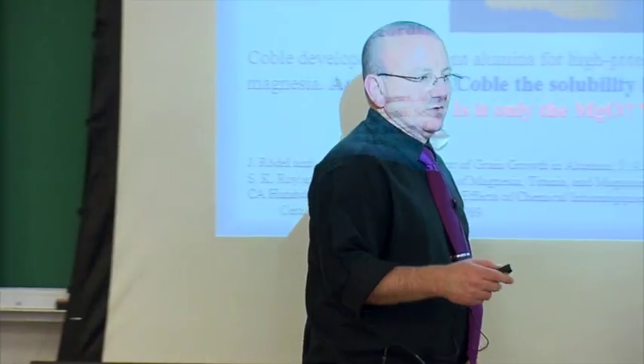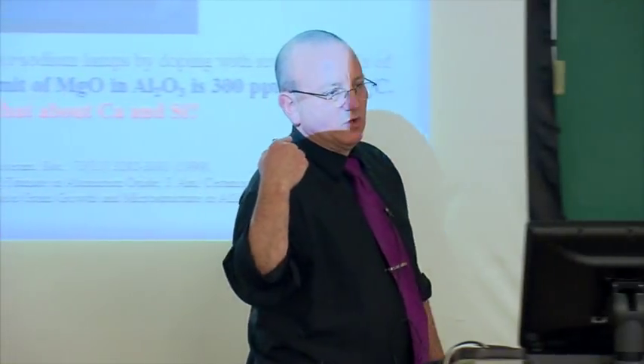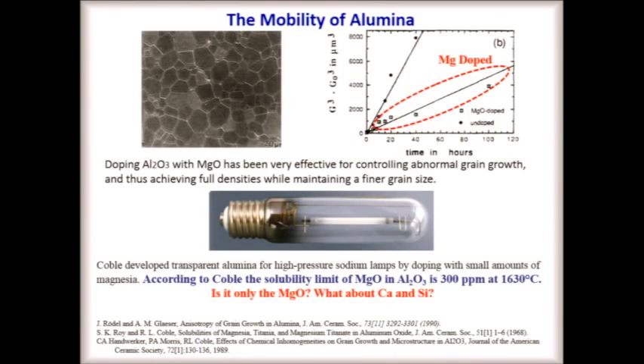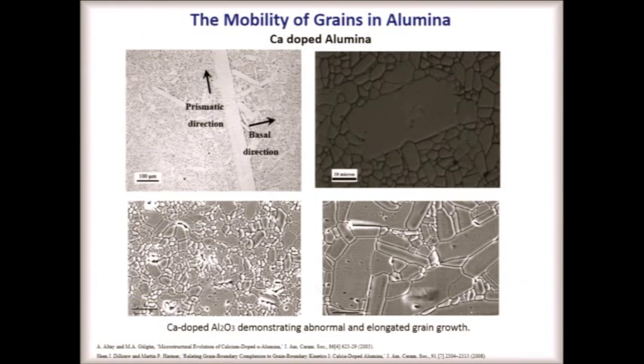The same can be said for those nasty impurities, and two of them I'm showing here, calcium and silicon, that cause exaggerated and abnormal grain growth. And once again, we add this stuff, but we don't often measure how much we actually have in there when we do the measurement. The example is magnesia, which has a high vapor pressure. So we can add 300 ppm, but I promise you, that's not what you've got in there. So it's really important to monitor this, and at the same time, it's very difficult.